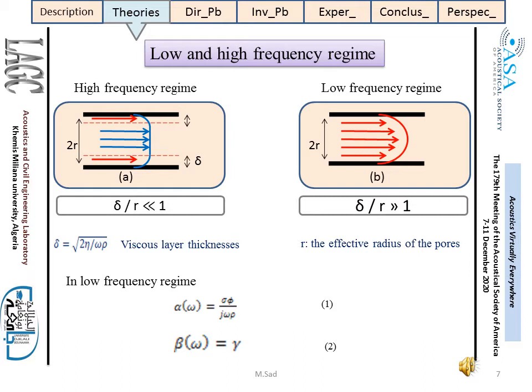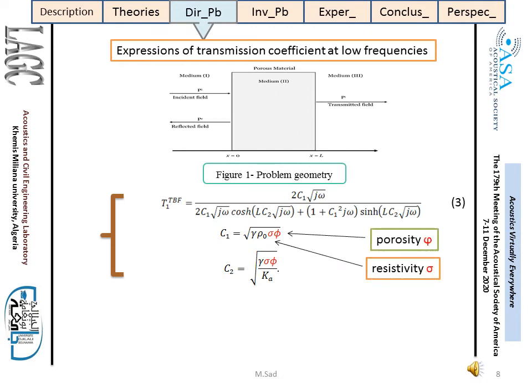After this presentation of the equivalent fluid theory and Biot theory as well as the definition of the different acoustic parameters, we will now proceed to the study of the direct problem. Let's consider a rigid porous medium with thickness L. Using the condition of continuity of the pressure and velocity fields at the boundary of the medium, we found the expression of the transmission coefficient T1 at low frequency. In addition to frequency, the expression T1 also depends on porosity and flow resistivity.